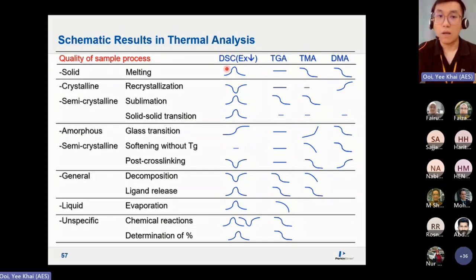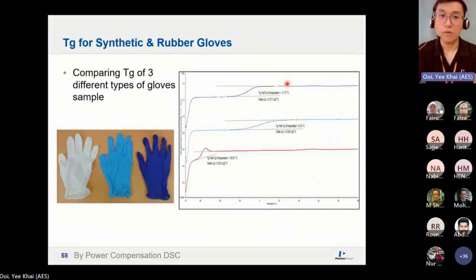Okay, so exo down. Endothermic melting is always endo, so it's like a peak. Crystallization is always exo, you can see. But as per usual, regardless of whether you are doing melting or crystallization, in TGA there is no weight change, hence no transitions. So this is what you have to be clear on, the concepts of decomposition and also melting. For example, like your glove material, the TG usually occurs at a very low temperature, as you can see, minus 60 or so. So we use DSC to check what is the TG for different types of rubber gloves.